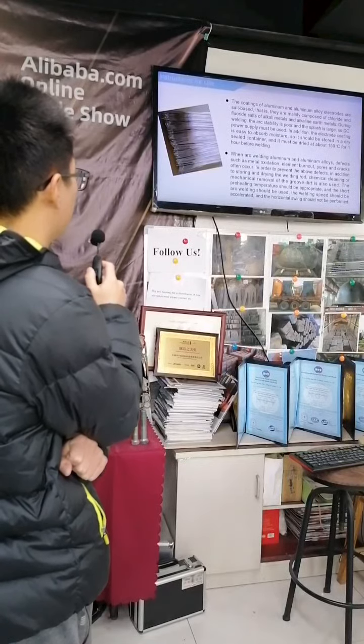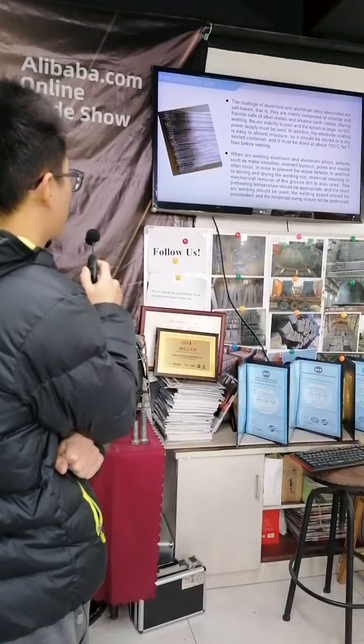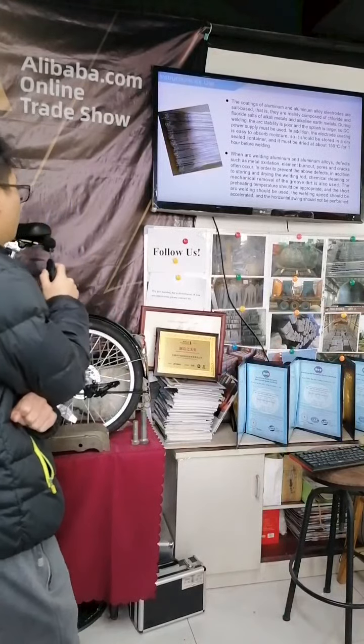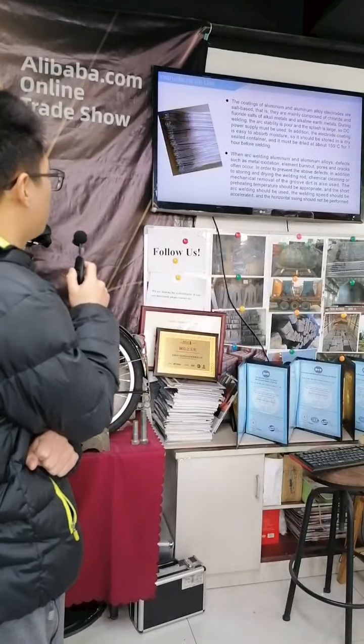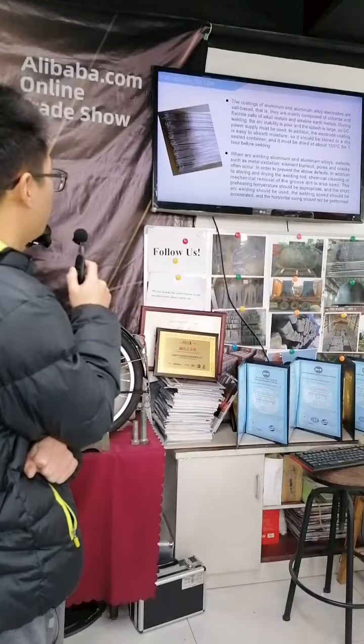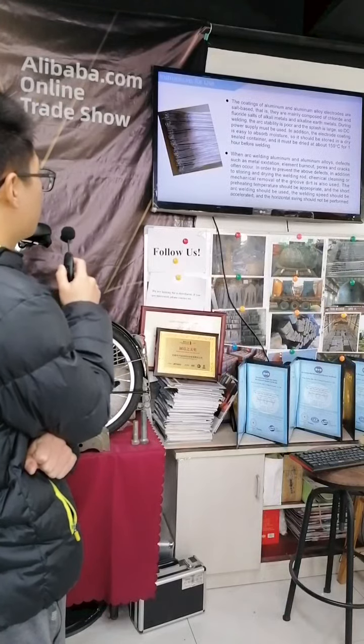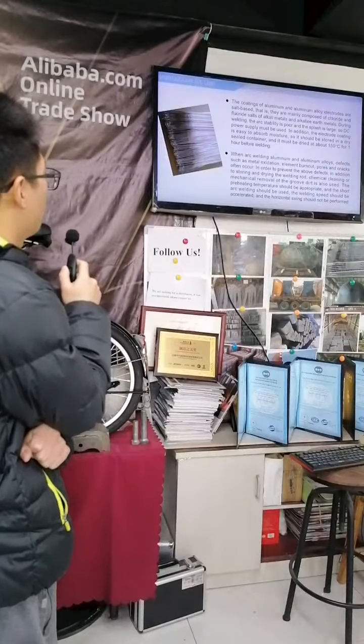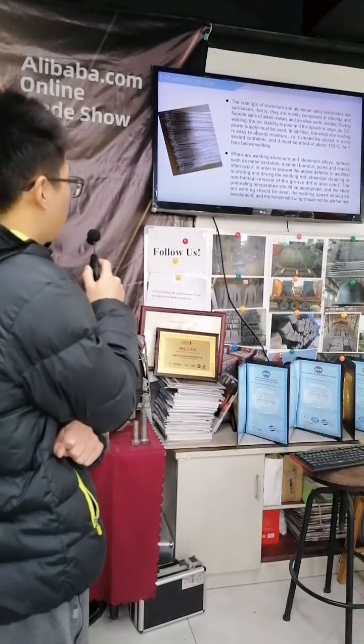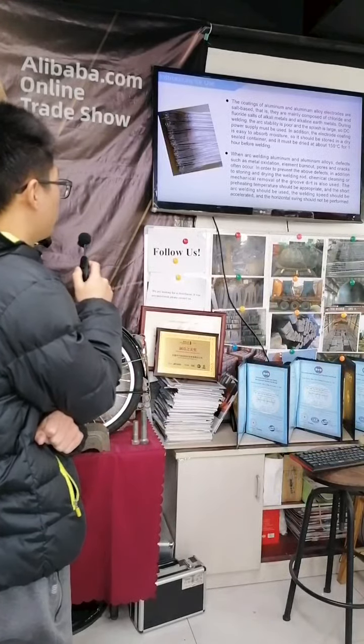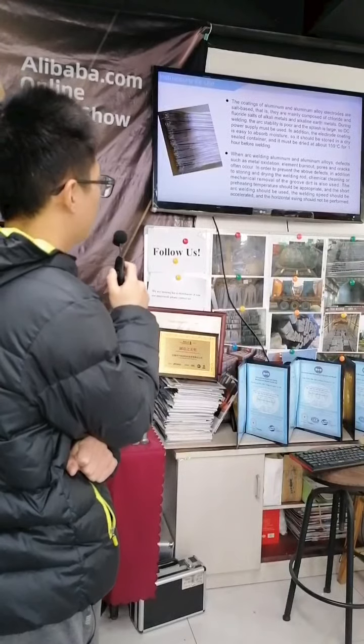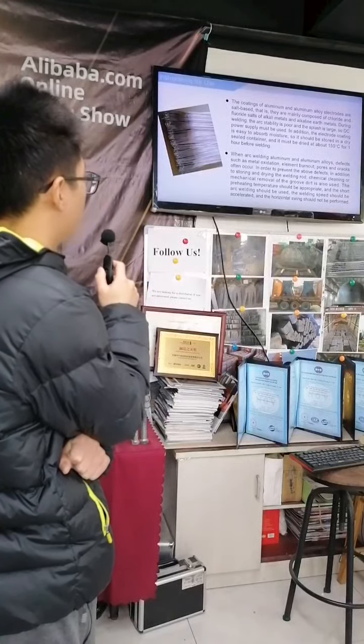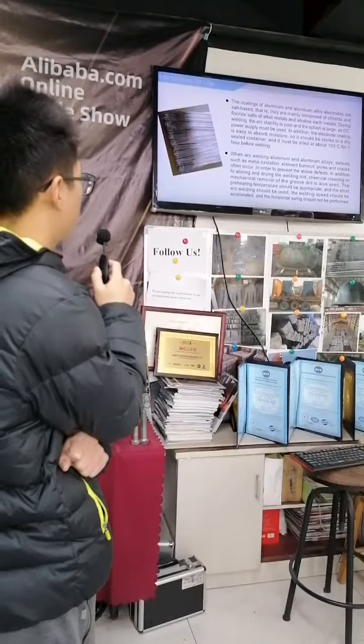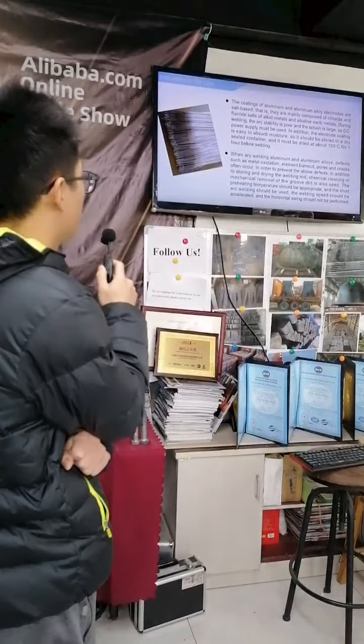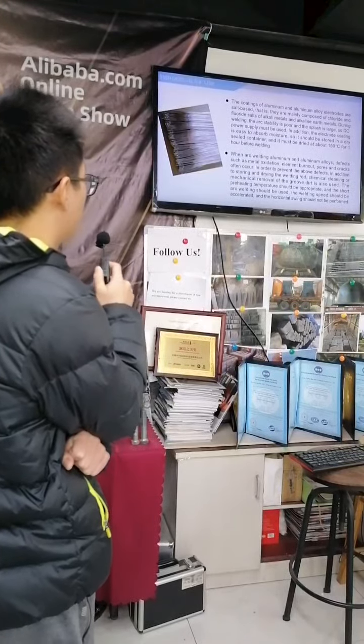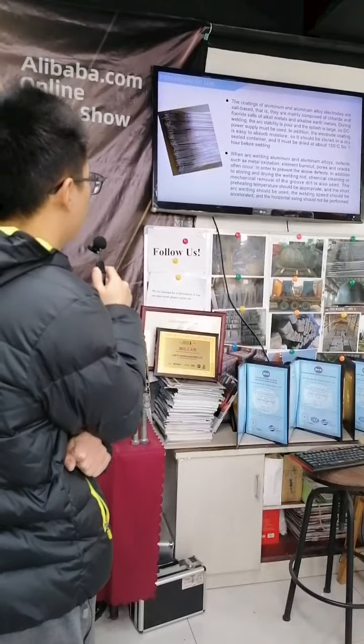When arc welding aluminum and aluminum alloys, defects such as metal oxidation, element burnout, pores, and cracks often occur. In order to prevent the above effects, in addition to storing and drying the welding rods, chemical cleaning or mechanical removal of the groove dirt is also used. The preheating temperature should be appropriate, and short arc welding should be used. The welding speed should be accelerated, and the horizontal swing should not be performed.